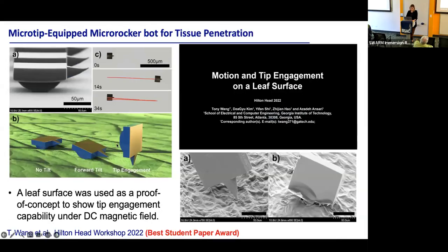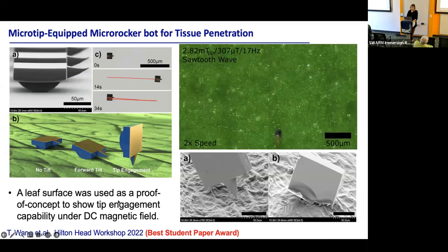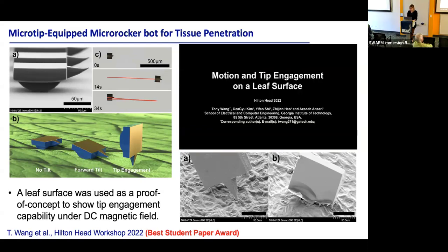So here I'm just showing that we printed little blades, and when we applied a DC magnetic field, this only has a thin layer of nickel on top. So under basically a sawtooth waveform underneath the stage, the robot is doing stick and slip, moving forward and backward. And then once we apply a DC field, the tip gets engaged and it can puncture, in this case, just a leaf. So now the DC gets applied and the robot is, on demand, tilting to align with the magnetic field, and it can engage its tip.